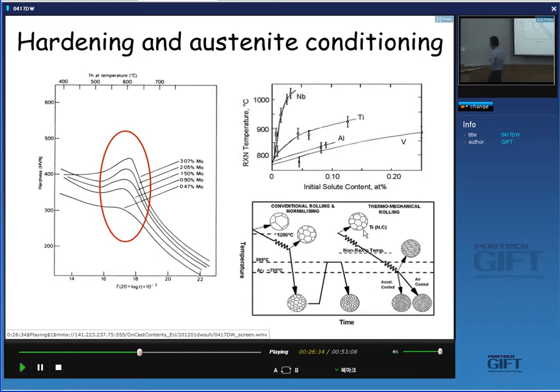So you can understand why we put carbide-forming elements into the alloy. One purpose is to increase the strength. The other is called austenite conditioning. When you heat up the specimen to hot roll the plate, it will be over 1200 degrees Celsius. Then you apply hot rolling and cool to the final form. When the steel does not have precipitates such as titanium carbide, niobium carbide, or vanadium carbide,